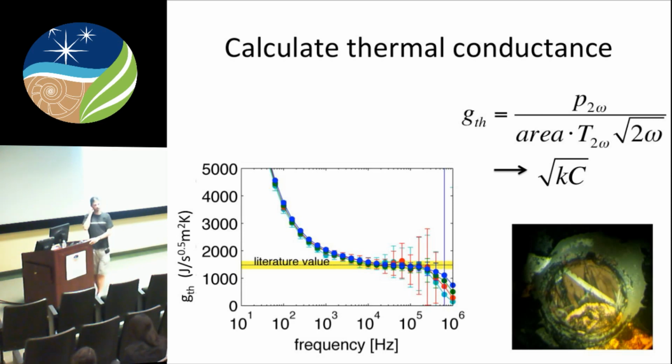For electrical conductance, it's not a concern to me because these are metals, so they already transport electricity. I don't think surface effects change the bulk conductance of metals like they do for non-conducting materials. For thermal transport, I haven't done enough work to show that it won't matter, because there is something called interface conductance. It's not really a quantum effect: vibrations in the metal might not propagate effectively through the monolayer interface with the surrounding medium.